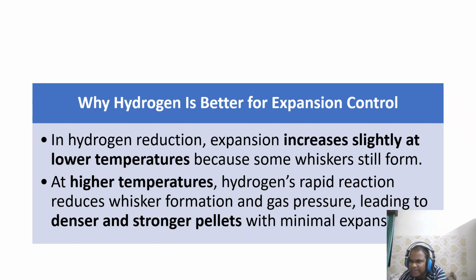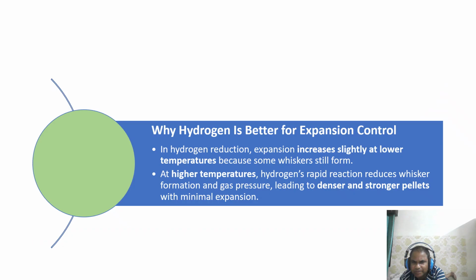Now, hydrogen at different temperatures, how does it behave? Here is the kicker. Hydrogen's magic depends on temperature. At lower temperatures, you might see a bit of whisker action, causing slight expansion. But crank up the heat and hydrogen's rapid reaction creates denser, stronger pellets with minimal expansion. It's like hydrogen turns pellets into steel superstars.